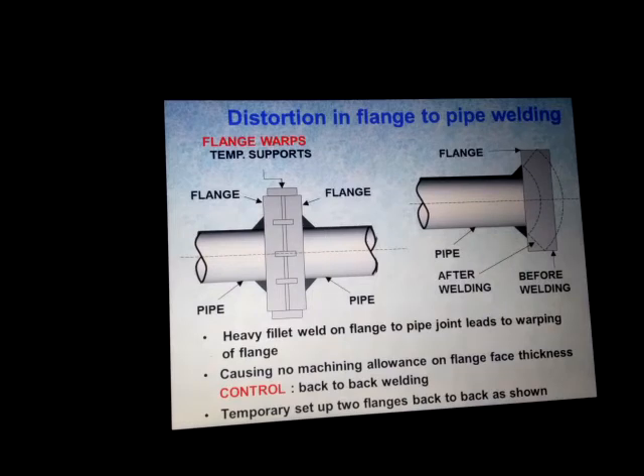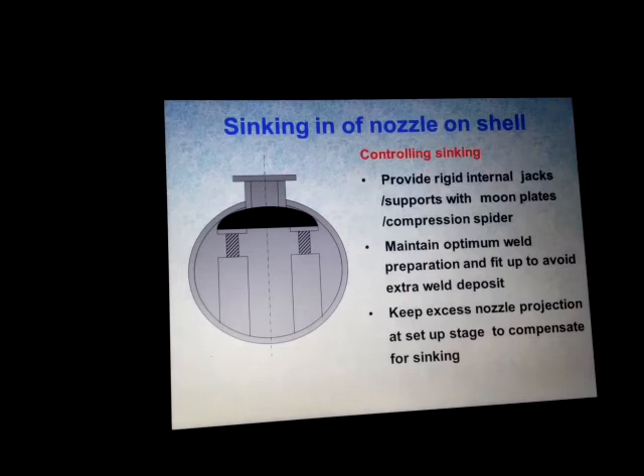Heavy fillet weld on a flange to pipe joint leads to warping of the flange, leaving no machining allowance on the flange face thickness. Control by back-to-back welding, with a temporary setup of flanges back to back as shown. Control sinking by providing rigid internal jacks and supports with moon plate and compression spider. Maintain optimum weld preparation and fit-up to avoid extra weld deposit. Keep excess nozzle projection at the setup stage to compensate for sinking.